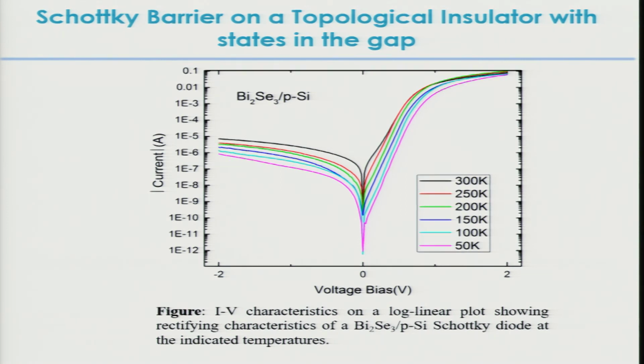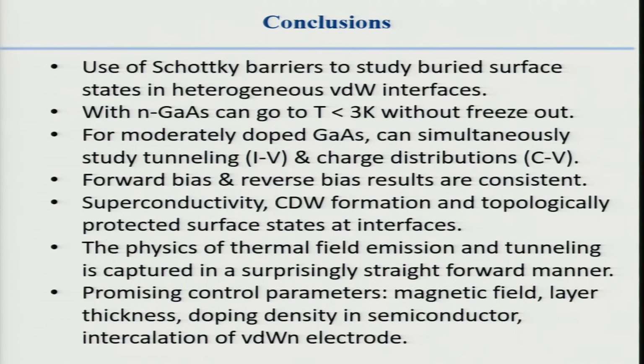And that's quick conclusions. We've used Schottky barriers to study buried interfaces. We can go with gallium arsenide's ideal substrate, especially if it's doped with silicon. We can do tunneling and capacitance measurements on the same moderately doped Schottky barrier. So you understand the barrier very well, and tunneling gives you transport through it. Capacitance gives you the charge buildup at the barrier, and that's what's helping us here.